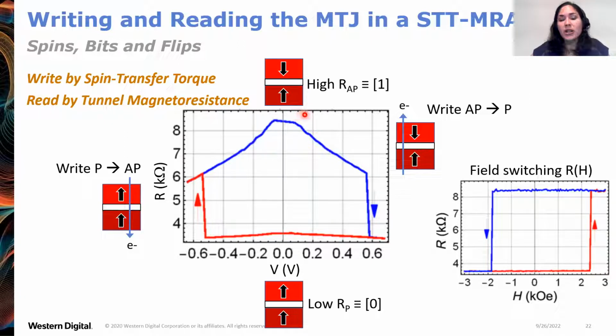When you want to flip the free layer to the parallel state, you apply a bias high enough to surpass the critical voltage for flipping till you get to the low resistance state, for example, a written bit of 0. Then when you want to write back to the high resistance state, you apply a bias in the opposite polarity, large enough to flip the magnetization back to the high resistance state.